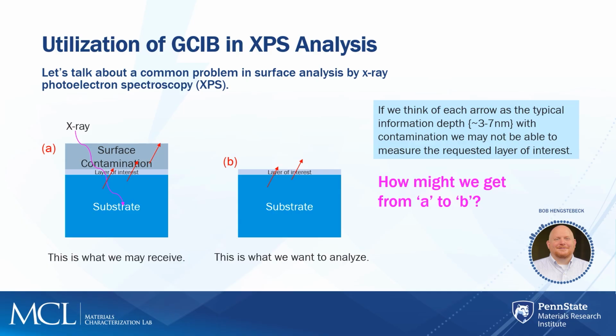And the reason for it is that in the surface characterization technique XPS, or similar techniques like TOF-SIMS or Auger, the typical information depth that we're working with is in the 3 to 7 nanometers level. So just a few monolayers of material is the signal that we're going to be analyzing. And for most materials that we go to analyze, they have to be handled and they have to come in with some kind of container.